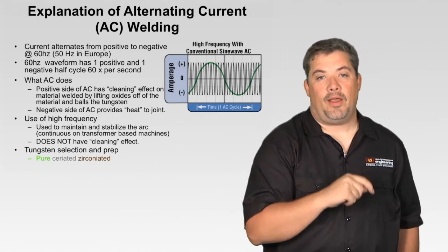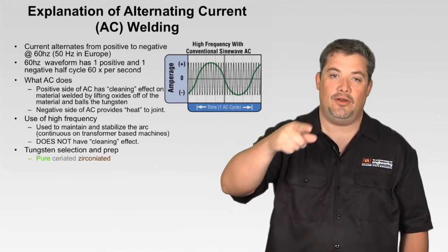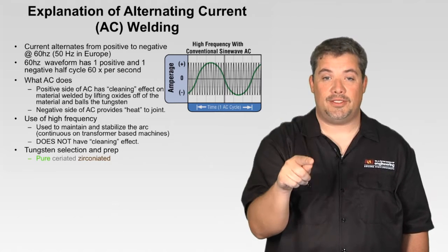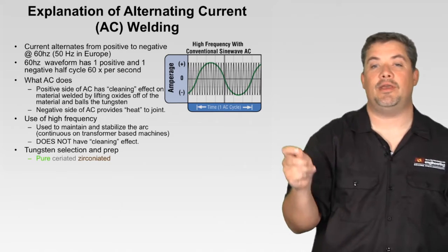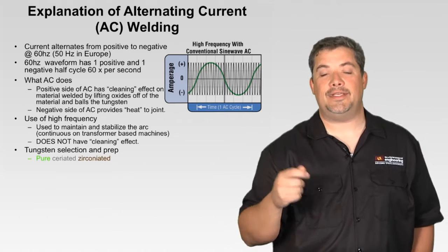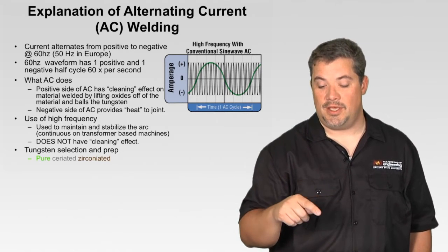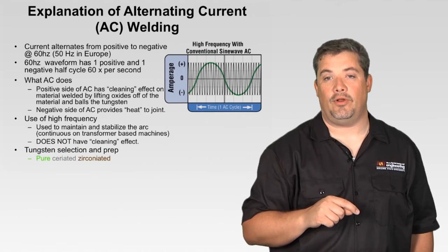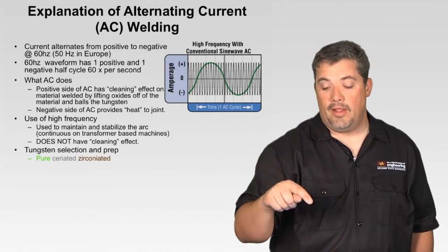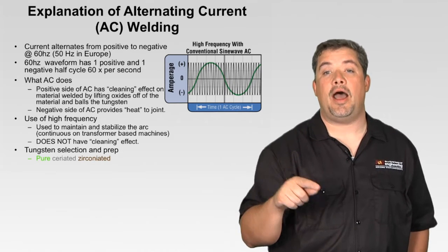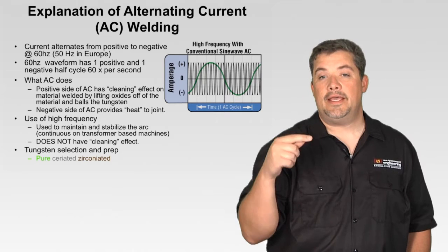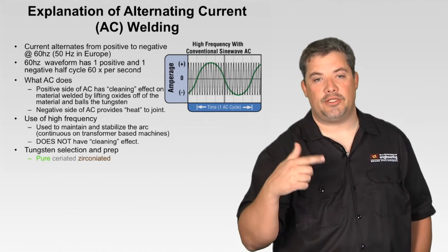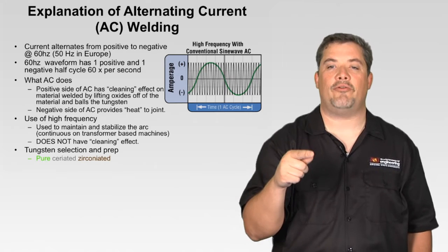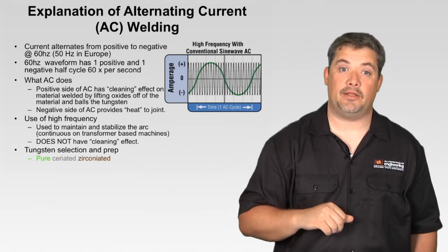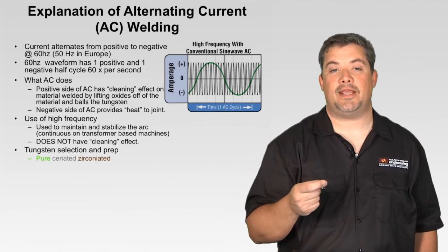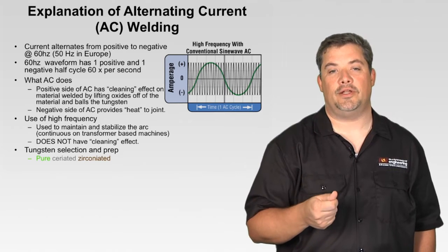The other thing about AC is because it does those changes, 120 of them every second, the arc literally shuts off and turns back on. So we use high frequency all the time on conventional AC welding. And in the illustration here, you can see the green line is an AC sine wave for a welding arc. The black line that's high hertz is high frequency. And that allows me to transition through that off point where the arc turns off and turns back on 120 times a second.